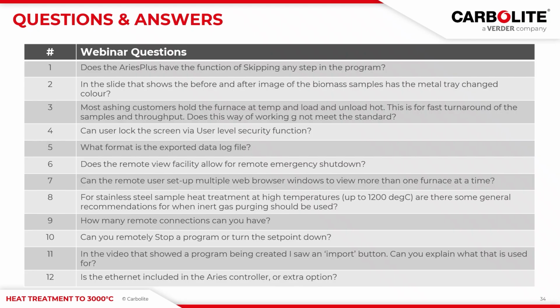Very good. Next question's around the process, really. So most ashing customers hold the furnace at a temperature and load and unload hot. This is fast turnaround of samples. Does this not meet the standard? Yeah, it very definitely does not meet the standard. I think the danger of adding samples to a hot furnace is that the burning will happen very vigorously, and it could lose some ash content out of the crucibles. So I think the purpose of the standard having this slow ramp rate from ambient is to try and drive off the volatiles slowly so that you don't get such vigorous burning. So no, doesn't meet the standard. Not this specific standard, at least.